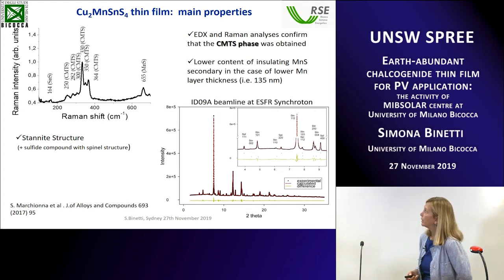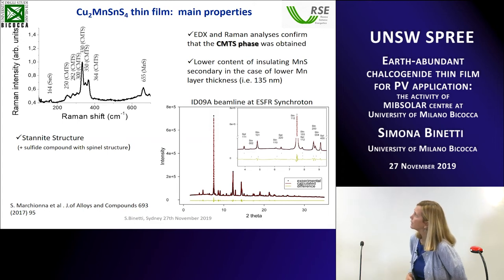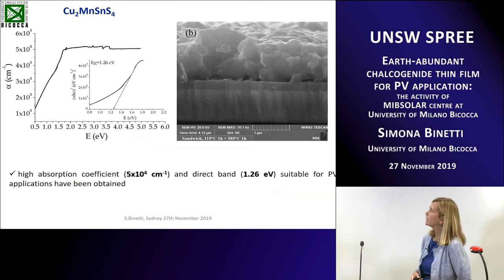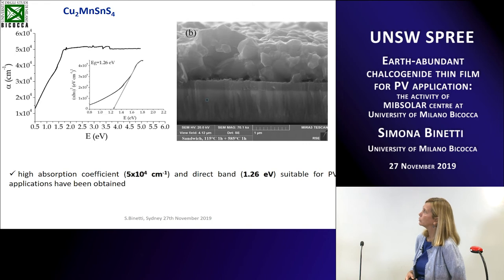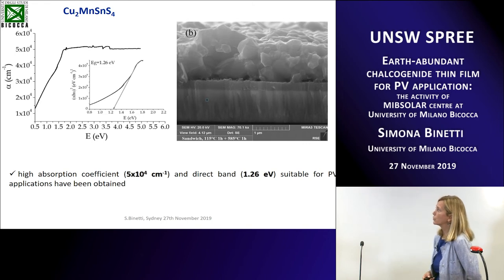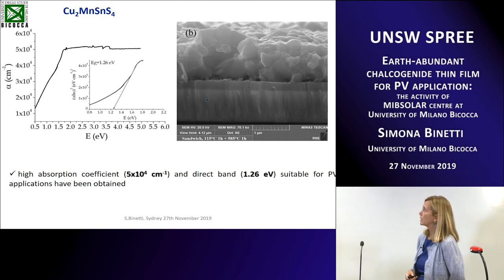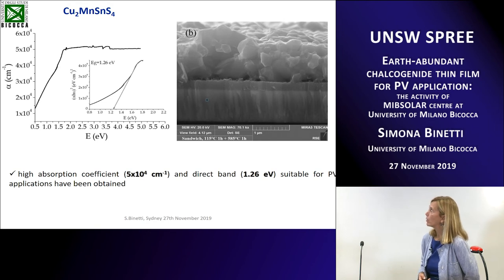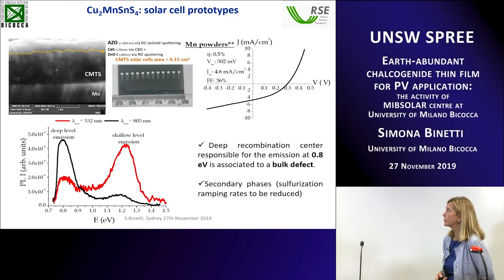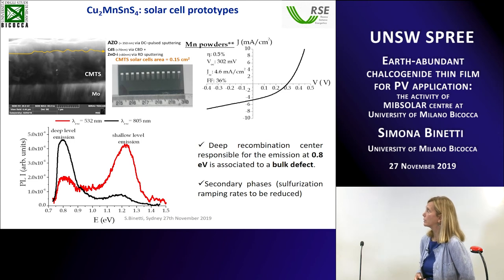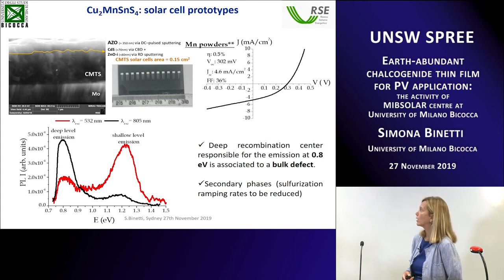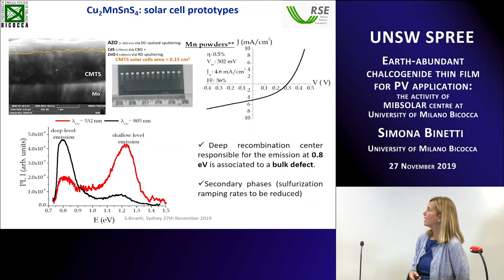The band gap is the right one, in the order of 1.2 eV, and this material also has a very high absorption coefficient, so it's suitable for PV application from this point of view. Our first devices had an efficiency around 0.5, so the best one. Of course, we performed several PV devices.